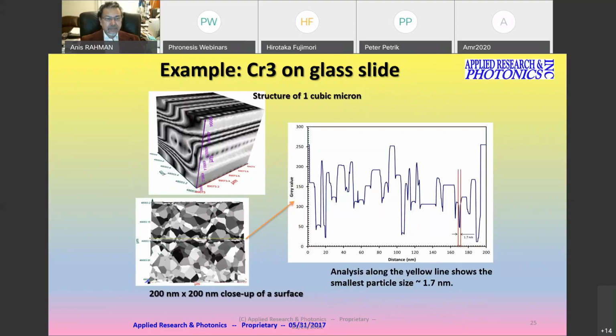Here is one of the very early works we did on chromium nanoparticles. As you can see, the particle size here is 1.7 nanometer. And when you do the profile along this line, then all the particle sizes can be measured and their distribution can be estimated.